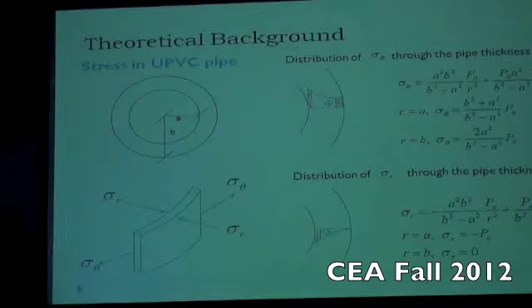Okay, the stresses in the UPVC. First of all, we assume that the concrete core takes all the axial compression. So you don't see an axial component here in the diagram. But in the transverse directions, the PVC is subject to a tangential stress, which is tension, and radial stress in compression. And the diagrams show the distribution of both the radial and tangential stresses through the pipe thickness.